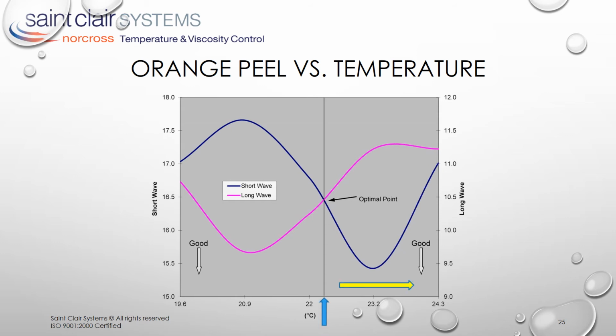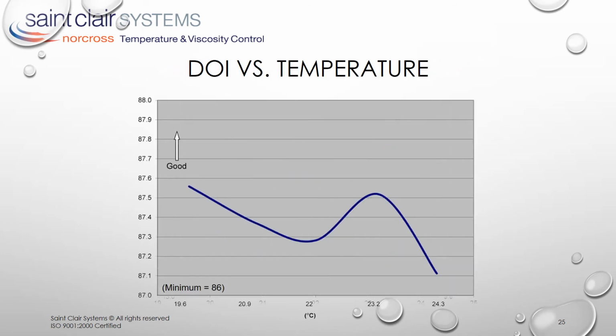Increasing in temperature towards 24 degrees C will optimize short wave performance over long wave. Conversely, reducing the temperature towards 21 degrees C will optimize long wave performance over short wave. With all other variables held constant, we can use coating temperature to control the orange peel of our finish. This provides total control over surface finish. It also explains why there's this nominal 3 degree sweet spot for finish quality that's always been the rule of thumb.